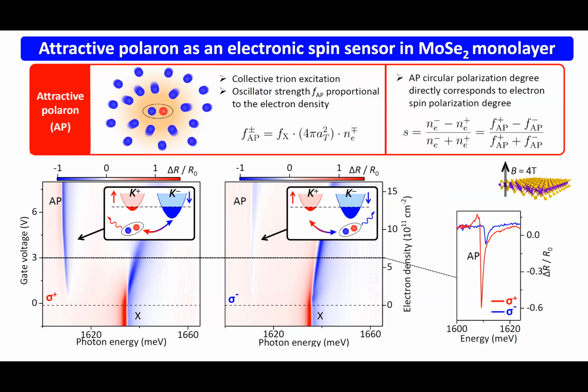Of course, in the absence of magnetic field, you have degeneracy, but the spins associated with the two valleys are different. And applied in-plane fields cannot mix these states with very different momentum, very different circulation. They will try to mix the spin states, which are split by spin orbit interaction. So you need an in-plane magnetic field larger than the spin orbit splitting, and that's not accessible. That's why we end up applying only out-of-plane magnetic fields.